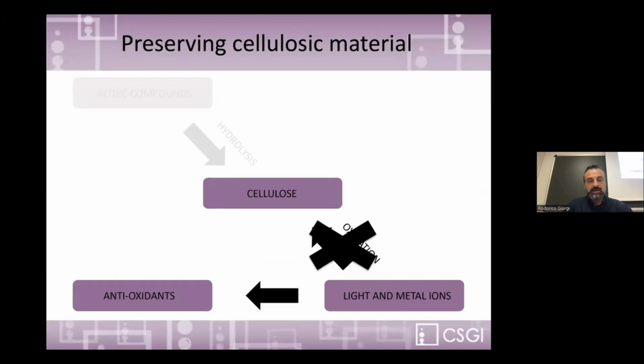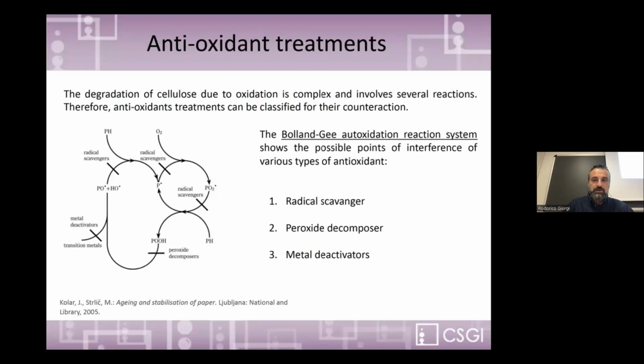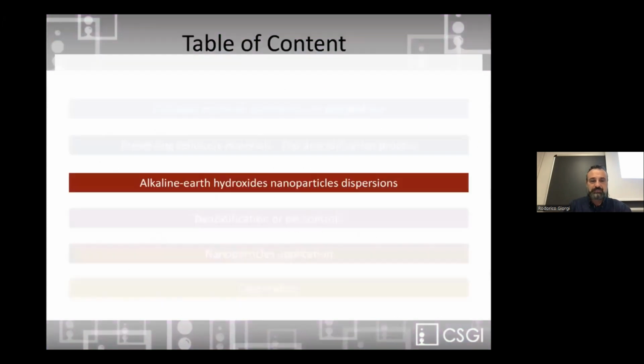And to inhibit oxidation, there are several methods that can be classified with the general term of antioxidant. You probably well know the Bolland-Gee autoxidation reaction scheme, where the loop the cellulose goes into can be stopped at several steps by using different materials, like a radical scavenger, peroxide decomposer, or metal deactivator, for example, the use of phytate. I want to show today, this morning, that the two processes are much more connected than expected.